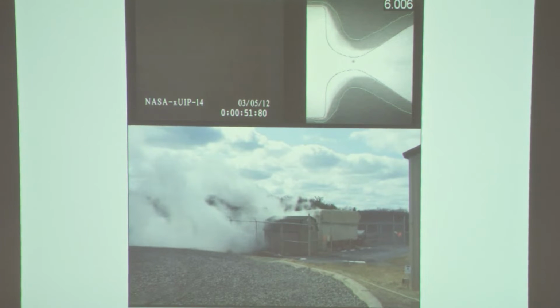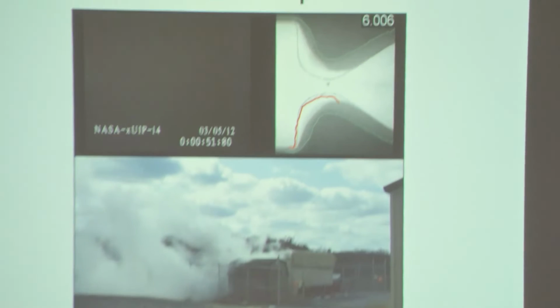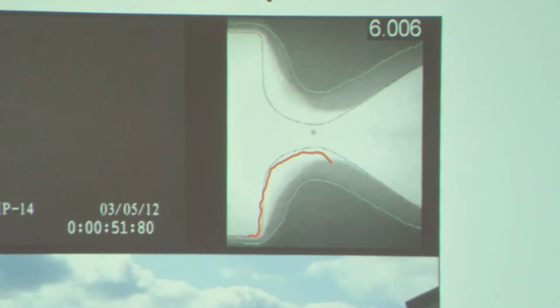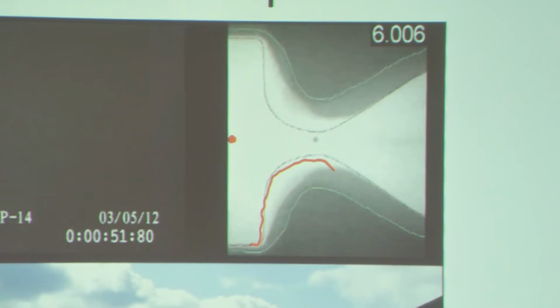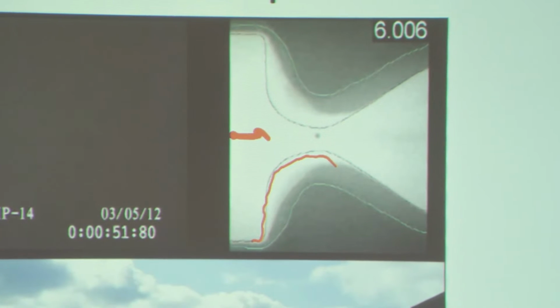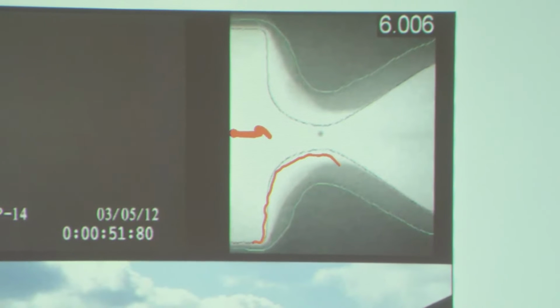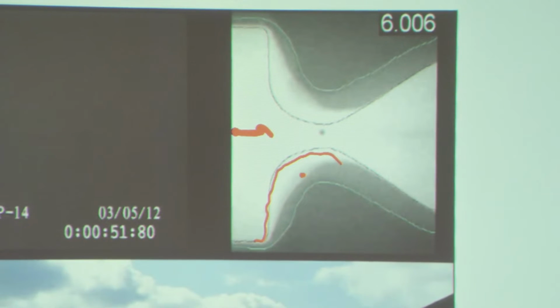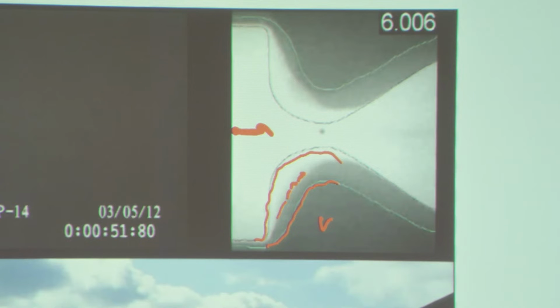This black line that was here was the original location of the nozzle. And then as the gases went through it from left to right, they started to erode the nozzle. And now you can see two different other lines. There's this fuzzy line here, and there's a green line here. Below the green line is the virgin material. Above the green line is the material in this carbon composite where the binder started to burn out. And this material here has become very porous.